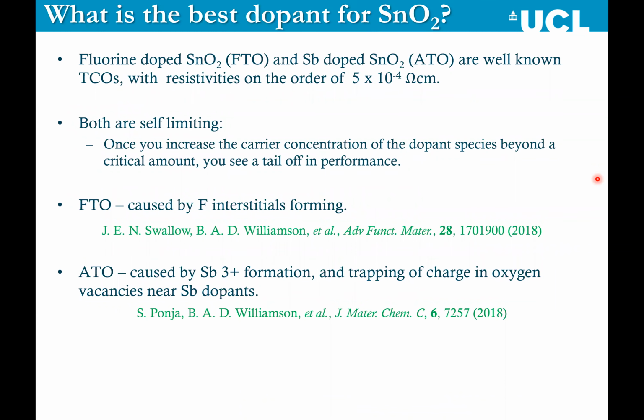So we were funded by Pilkington NSG, which is this very large glass company that I was mentioning. And they are the world's largest producer of fluorine-doped tin dioxide. And it's used for many of their ranges. You can get samples of their tech range, basically with any mobility up as far as a mobility of about 30 centimeters squared per volt second.